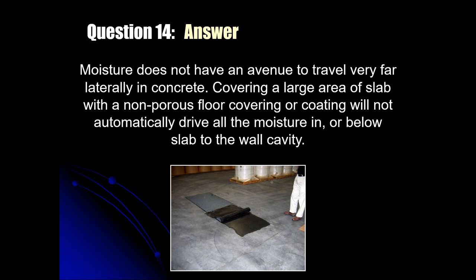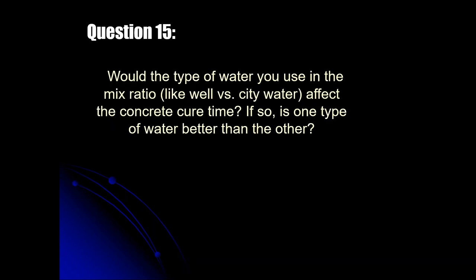So I put a rubber doormat down for a week and came back, peeled it back, and it's wringing wet, soaking wet underneath that mat. The point is, though, it was as wet, dark and wet to the outside edge of that mat as it was in the center. If moisture were traveling laterally to any degree, I would have expected to see a gradient where it would be lighter on the outside and progressively darker to the center. It's just not the case. So I'm not concerned. Now, obviously, if you have gypsum wallboard in direct contact with the surface of the slab, yeah, you can have some concerns, but that's not the recommendation for installing gypsum board.